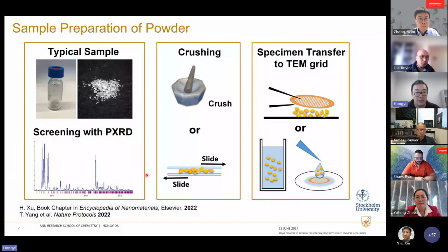So for powder samples, it's actually very simple. We take a powder, a pharmaceutical compound, and then we just crush it and deposit it onto the TEM grid. Usually what we do nowadays is to do a PXRD screening first to see if the powder is crystalline. This also gives us the expectation of how much resolution we can get from the powder. And it's a very good quality control also.